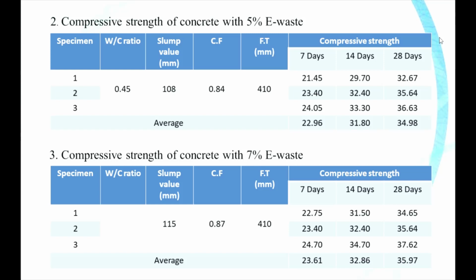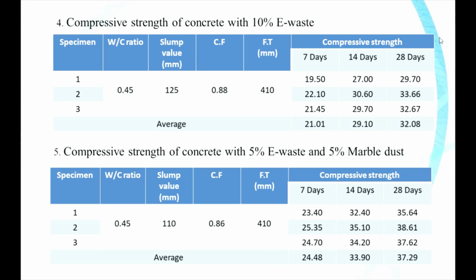So moving towards the next table, that is 10% addition of e-waste. The water cement ratio is the same as in the previous table, that is 0.45. Slump value is 125 mm. Compaction factor value is 0.88. Flow table value is 410 mm. So averages of strength at 7 days is 21.01 megapascal. At 14 days there is a strength of 29.10 megapascal. At 28 days there is a strength of 32.08 megapascal.